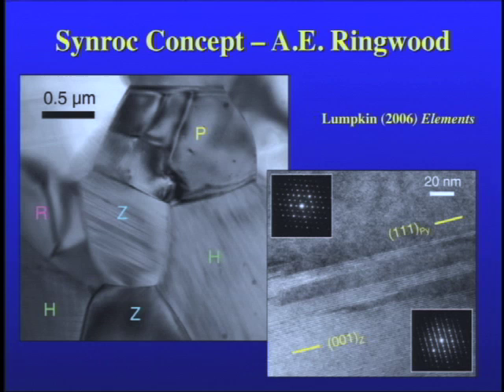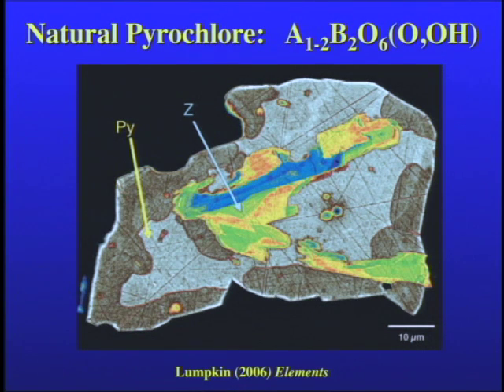This is a TEM micrograph, and one of the phases, zirconolite, was the host for the actinide elements in the waste stream. Now, zirconolite received a lot of attention. We studied the radiation damage effects, but it had a problem, and that is when we put too much plutonium in, it changed to pyrochlore. And here's a high-resolution image of zirconolite, still crystalline, with the lattice-fringe-free regions indicating that the pyrochlore is amorphous. Well, this was interesting, and so we studied natural pyrochlores just as we studied natural zircon. We found zirconolites surrounded by pyrochlore.